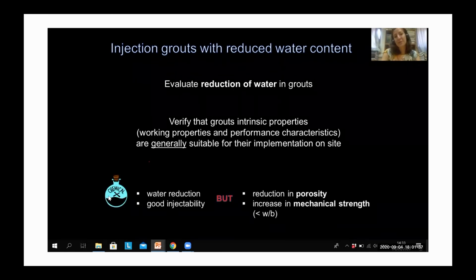So we know that there are some chemicals such as plasticizers and superplasticizers, which allow a strong water reduction and lead to very good injectability. So why not use those directly? Well, there are some problems, because if water reduction is massive, there is a strong reduction in porosity, and as a consequence, there is an increase in mechanical strength. So this research tried to reduce water while avoiding this kind of chemicals. Also, very often these chemicals are soluble salts forming, so that kind of defeats the purpose. So they were not used.